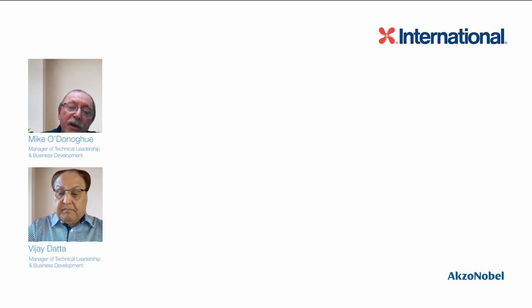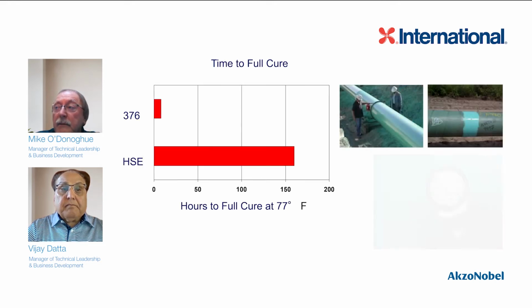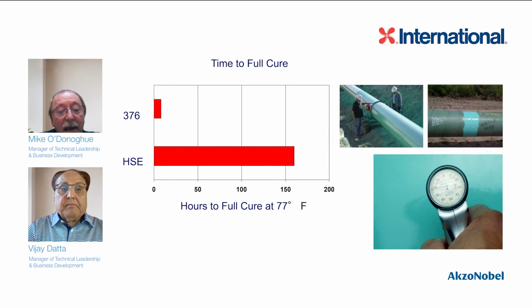376 curing, Vijay, you were mentioning the speed. Regular epoxy thin film, for example, would take 7 days at 77 Fahrenheit to cure. But with the technology we're describing today, Enviroline 376, the curing is so fast that you can walk on the coating very quickly in a tank or handle a pipe very fast, 8 to 10 hours of curing. So even when you have a Shore D of around 80, it's that fast to cure.